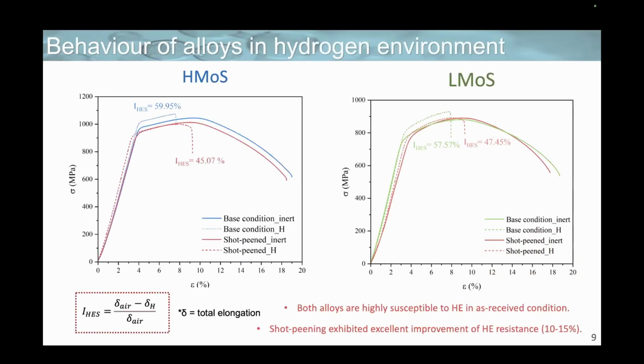The results of SSRT show that in as-received condition without shot peened layer, both materials are highly susceptible to hydrogen embrittlement. However, after we apply shot peening treatment, we exhibited an excellent improvement of hydrogen embrittlement resistance between 10 to 15%, which was calculated based on a total elongation.